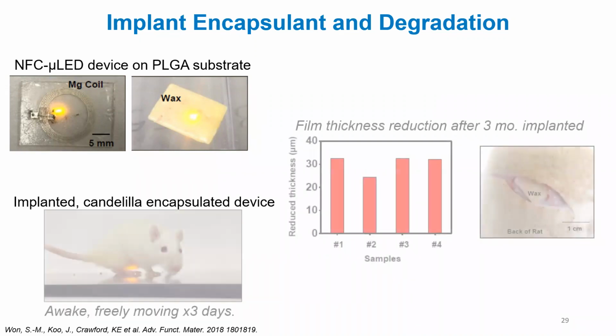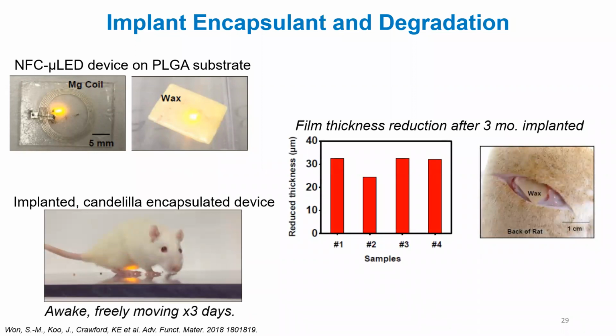And then what we next did was we implanted it into an animal model. And so I'm warning you because I'm going to show you what that looks like after we implanted it. We did this in a small animal model for 3 days. It was an awake, freely moving rat that seemed to not realize that there was a device there. This is important for areas like optogenetics. If you have questions about that, we can talk about it afterward and what some of the significance of optogenetics is. But after 3 days, there's a problem. Wax is a brittle material. So while it's really good as a water vapor barrier, it's not very flexible.